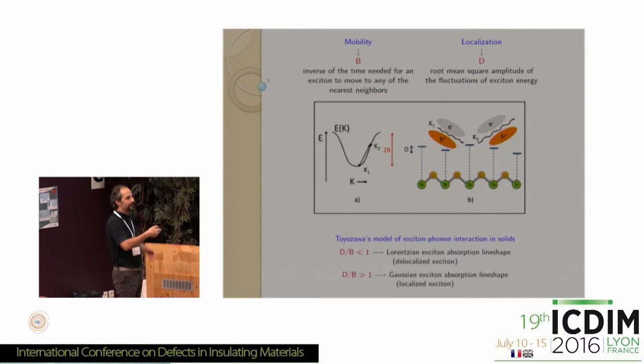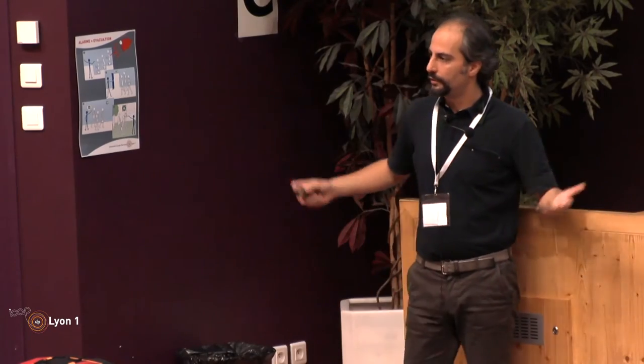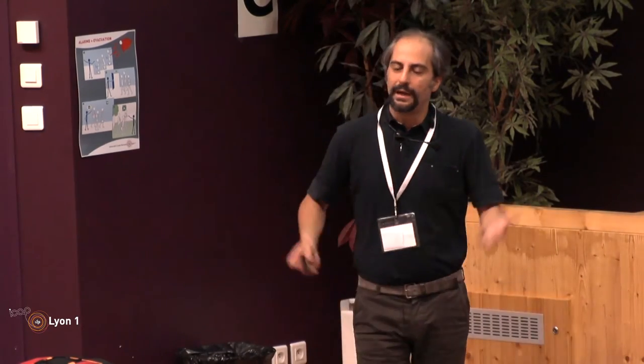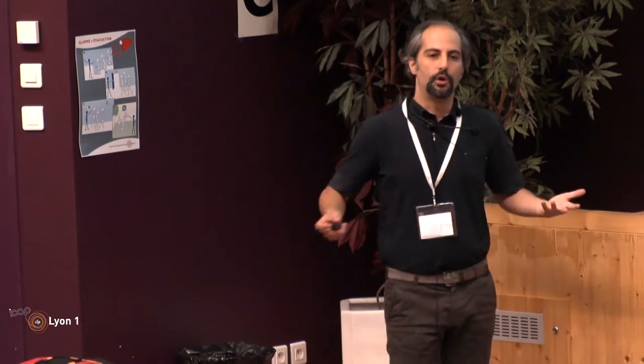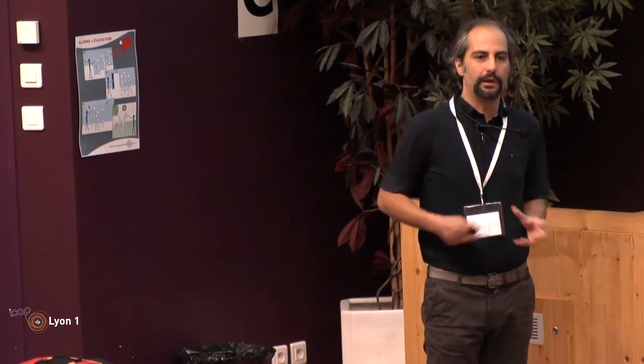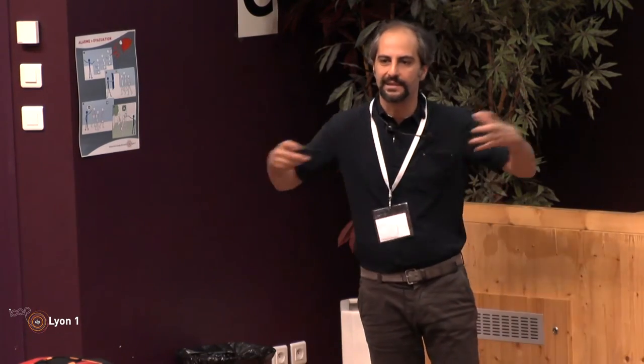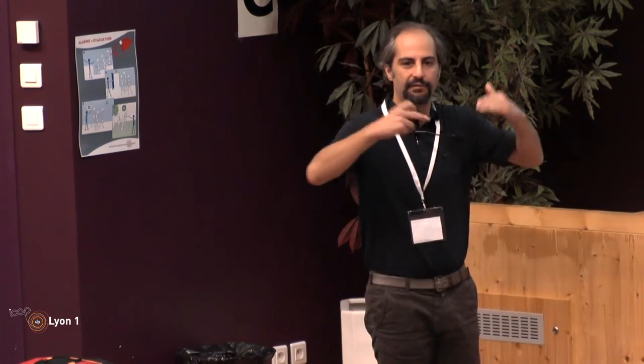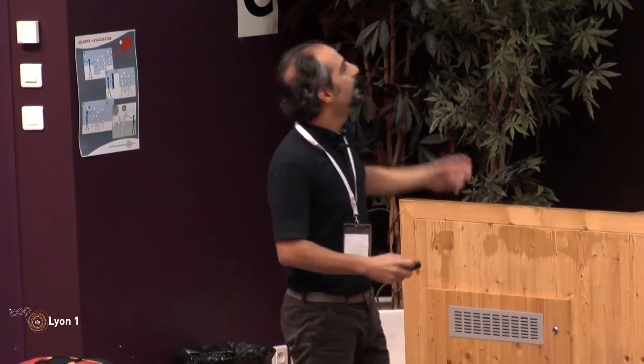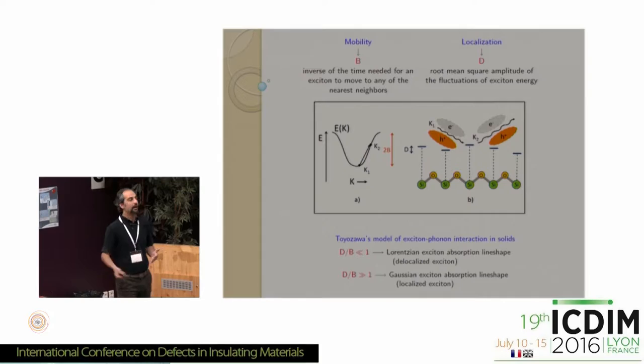Now, in a real system, you will always have some fluctuations from site to site of the energy of the excitonic state. This arises from thermal disorder, if you have a crystalline system, but if you have an amorphous system, they arise also from structural disorder. So in principle, in an amorphous system, not all sites are precisely equal, so you have necessarily some fluctuations from site to site of this energy. Now, theory predicts that the behavior of the exciton is completely different depending on the relation between B and D, so mobility and fluctuations.